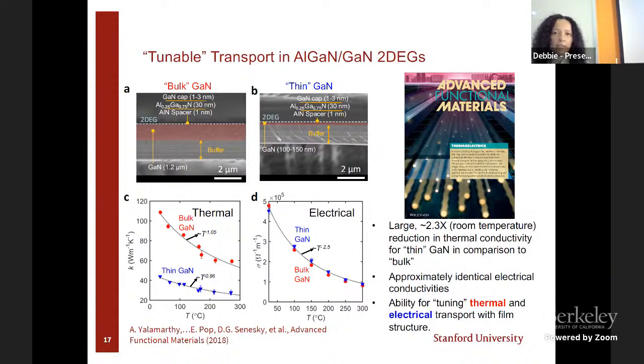We also studied the thermoelectric behavior, so another type of transduction. If we have heat gradients across the 2DEG, what happens? Can we use this as an energy harvester? One challenge with thermoelectric devices is the trade-off between electrical resistivity and thermal conductivity. So what my former student Anand Yalamarthy conducted was, can we change the thermal conductivity of our gallium nitride by changing the thickness of our gallium nitride layer? If we have a thick gallium nitride or a thin gallium nitride, that will change the temperature gradient or the thermal properties across this film here.